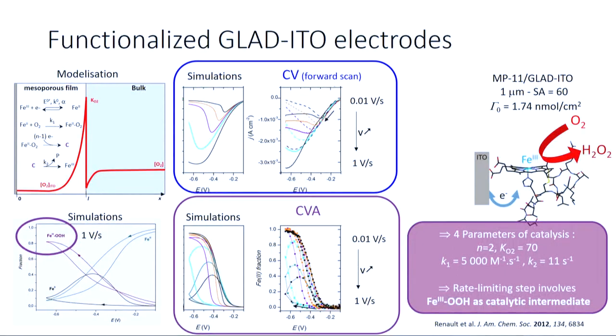But what is more interesting here, and what I want to emphasize, is the distribution of the catalyst in the nanostructured electrode at high scan rate once you reach the reverse potential. What you can notice is that at this reverse potential, which is a very low potential, you have neither the resting iron 3 state nor the reduced iron 2 state, but what you have accumulated in the network is an intermediate state, an iron 3 hydroperoxide, which is the state of the catalyst associated with the rate limiting step of the catalytic process. So this is the interest of this technique for operando analysis of a catalytic process, quantitative analysis of the catalysis mechanism, and identification of a catalytic intermediate.